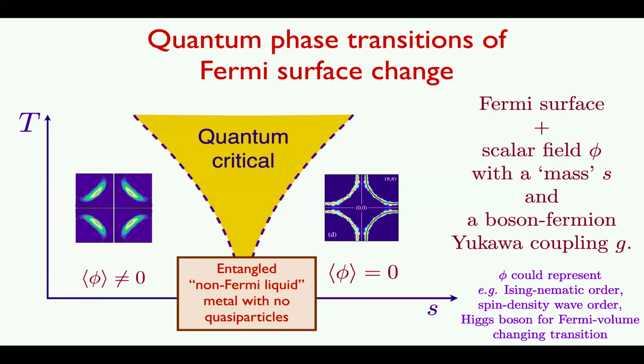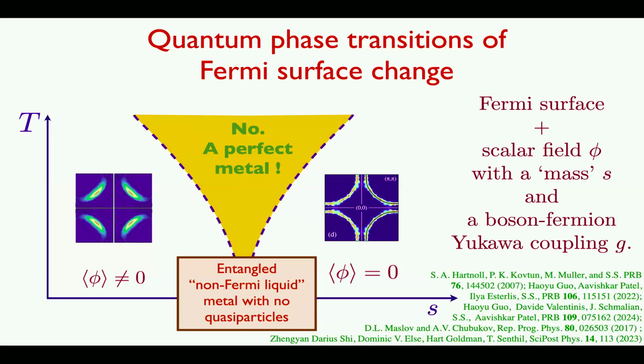This has led to the hope that once we understand the zero temperature state, we will also understand the strange metal as a manifestation of the zero temperature criticality at finite temperature. But slowly in the past decade or so, it's become clear that's a misplaced hope. If you take a perfectly clean system describing this quantum critical point, the finite temperature state is a perfect metal. It doesn't show any of the characteristics that I described from the experiments earlier. So what's the missing ingredient?